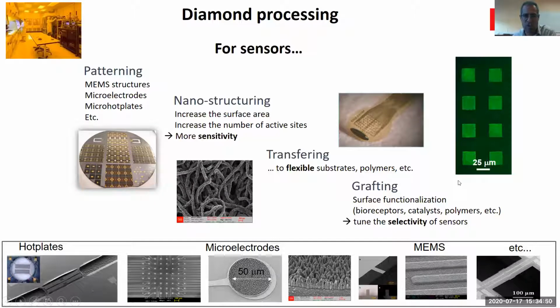We can also nanostructure these diamonds. You have an example here of diamond that was grown on carbon nanotubes. Again, these are nano size, they're very small. By doing this on the surface of a sensor, we can increase the surface area of our sensors, and therefore the number of active sites that will respond to an analyte, and therefore we can increase the sensitivity of our sensor. We have some technologies also to transfer these diamonds onto flexible substrates for sensing applications where we want to go in a pipe or things like these.